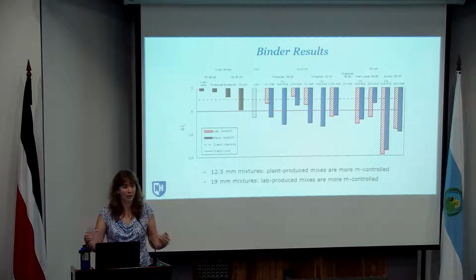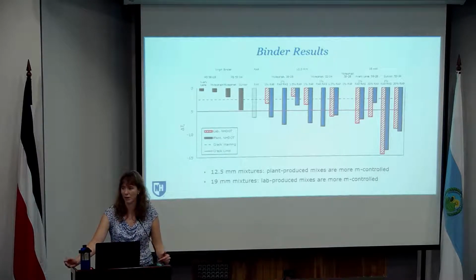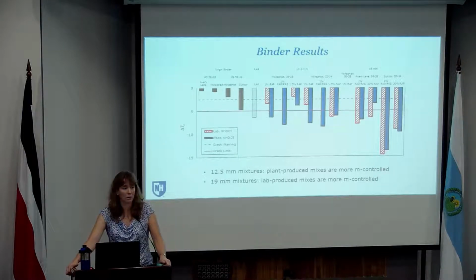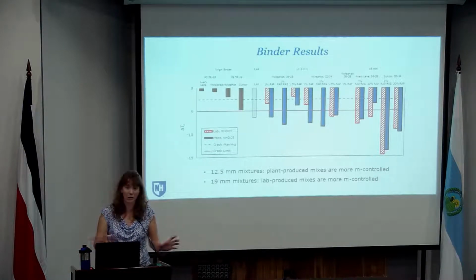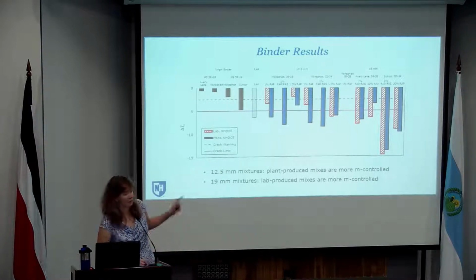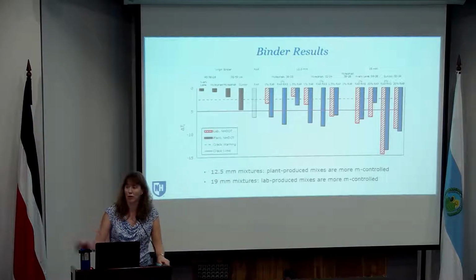Okay, and that was identified, I don't know, about 10 years ago as potentially problematic. So a lot of work went into identifying the presence of this material, which is relatively easy to fingerprint because of the heavy metals that end up in the material. But what it's shown to do is when it ages, okay, it'll meet the requirements in terms of the PG grading, but then when you look at how that material ages, and also when you look at something like the delta TCR, you're losing that relaxation capacity relatively quickly with that material.